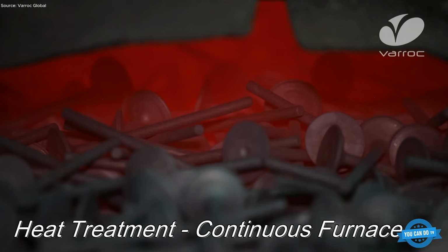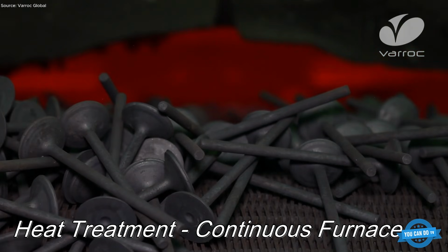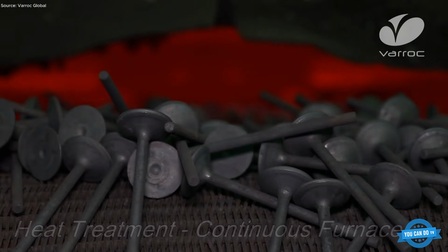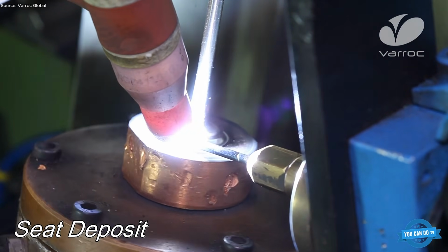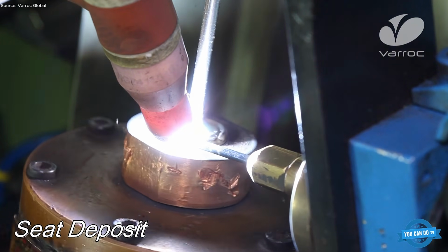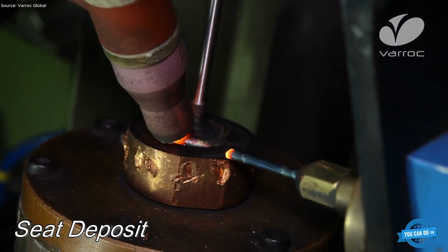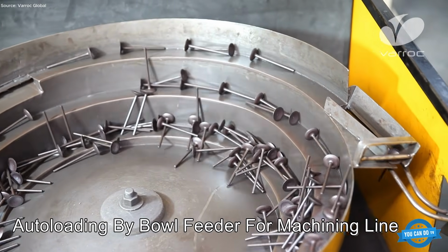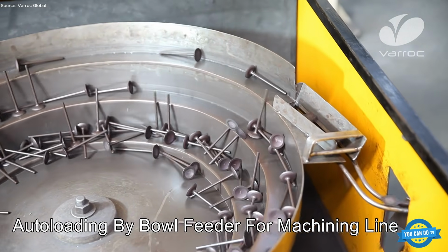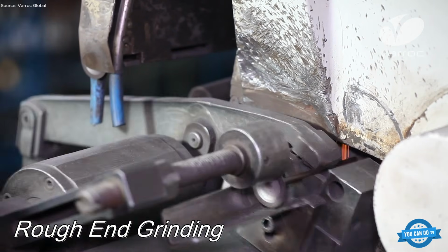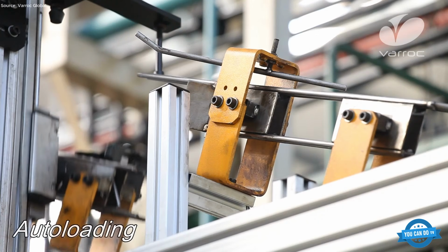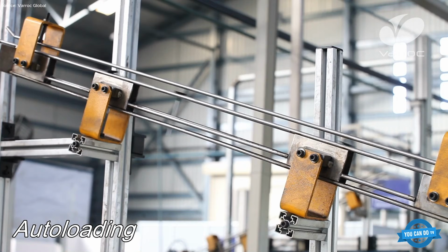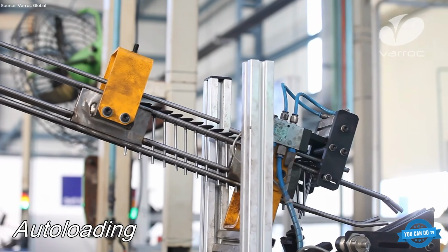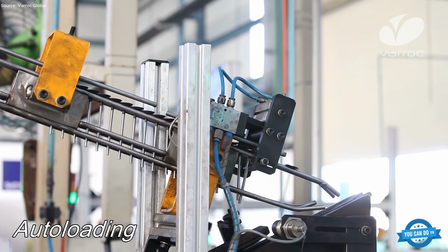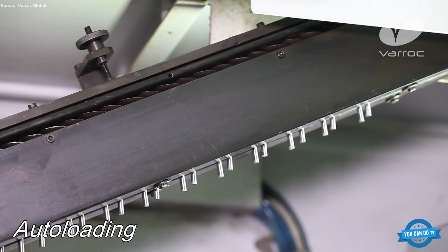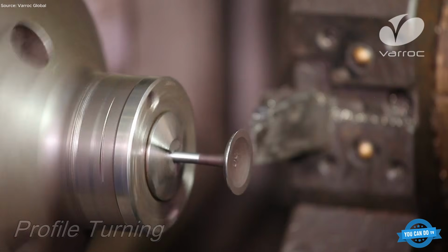The forged valves pass through a continuous furnace heat treatment, where temperature profiles are tightly regulated to achieve the required hardness, toughness, and microstructure. A seat deposit is then applied, typically using advanced alloys to enhance wear and heat resistance at the valve-to-seat interface. The process continues in the machining area, supported by auto-loading systems and bowl feeders that ensure consistent, high-throughput handling. Rough end grinding establishes initial dimensions, followed by automated transfer-to-profile turning, groove grinding, and head diameter turning and facing, where final geometry is progressively achieved.